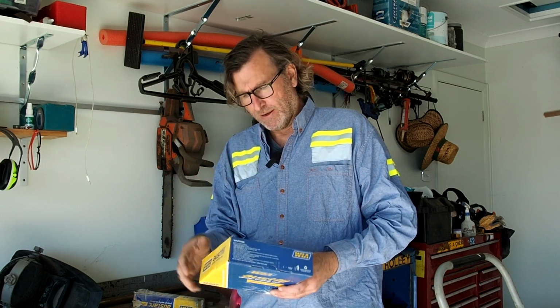Okay, so as you saw, the welding on the boat wasn't very successful. So what I've done, I've come home and I've pulled up on the internet the problems that I was having, and the Google searches that I found basically didn't show very much that I didn't already know, except for one thing, and that was the polarity that I was using on the wire. So I didn't even think about it at the time, but this OSFIL 11 is a negative or electrode negative polarity. Now when you use it the opposite way, you get a lot of spatter and you get cold short, which is a crack as something's cooling down, or it's more prone to cracking when it is cool. So which is ideally what you don't want in a boat.